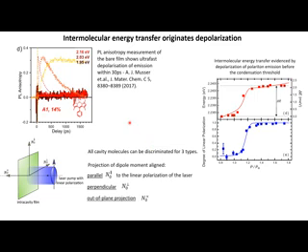But in densely packed organic films, it is very well known that there is a Förster resonance energy transfer between molecules, due to the dipole-dipole interaction. And this energy transfer is very fast in organic materials. In our organic system, it was shown in the group of David Lidzey that it happens within 30 picoseconds. So if we predominantly excite with linear polarization those molecules which have a dipole moment parallel with the laser, then within 30 picoseconds the polarization would be randomized over all other projections as well.